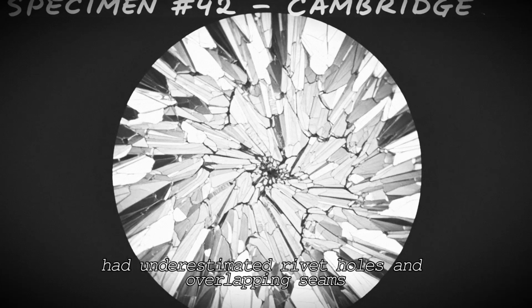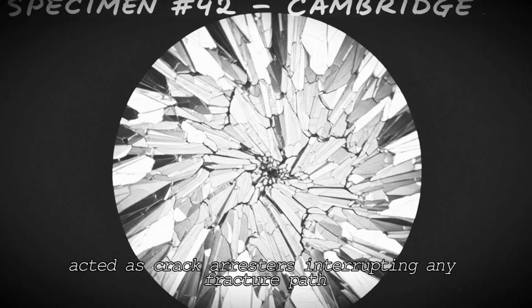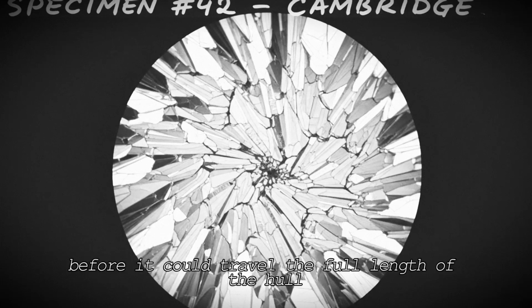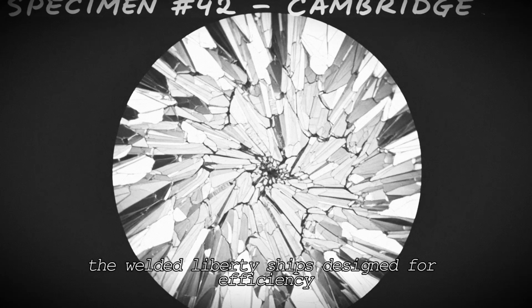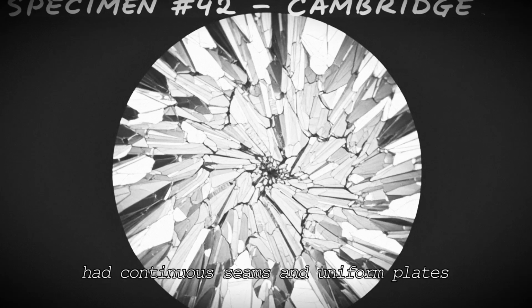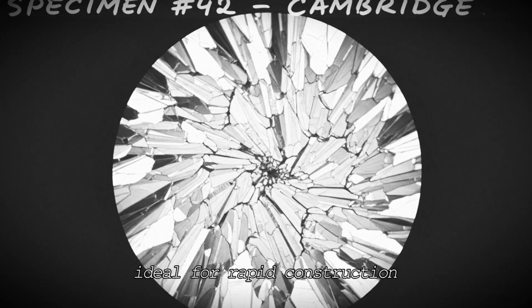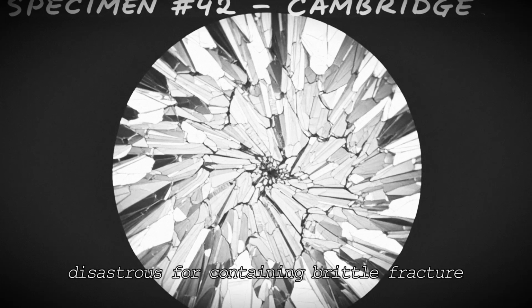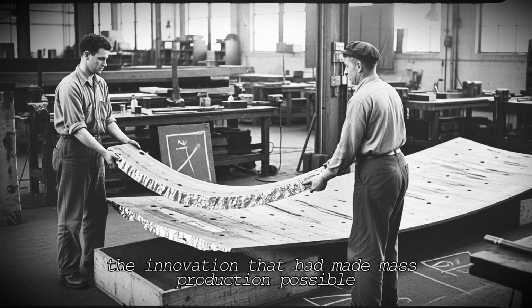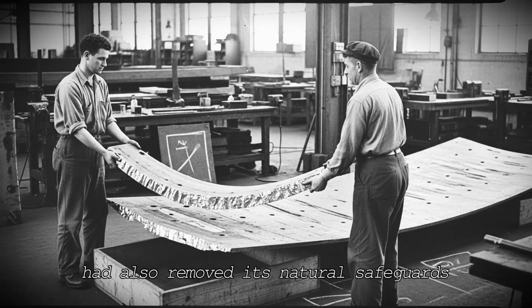Rivet holes and overlapping seams acted as crack-arrestors, interrupting any fracture path before it could travel the full length of the hull. The welded Liberty ships, designed for efficiency, had continuous seams and uniform plates, ideal for rapid construction, disastrous for containing brittle fracture. In effect, the innovation that had made mass production possible had also removed its natural safeguards.